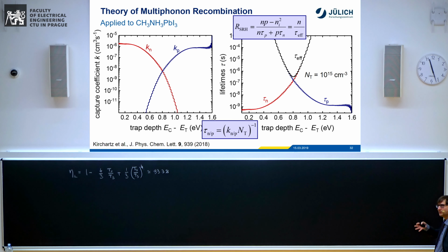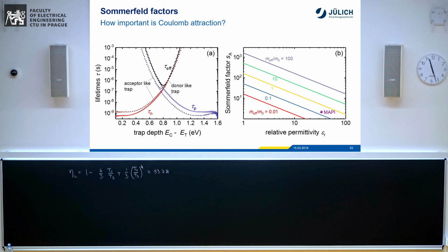Yeah, this is at least what a relatively simple theory of one transition only would predict. Now you can think about what kind of other situations you could have, like more than one defect to defect transitions, and so on. But in this simple case, it would very easily explain why the material is defect tolerant.